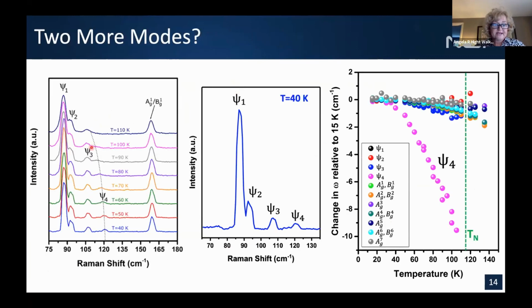So as we cool down even further, remember that transition temperature, the Néel temperature, was near 118. We begin to resolve two more features, such that if we blow up the 40K, we actually can now count 4 modes. So what we plot on this far right is the temperature dependence of all the regular phonons, as well as these 4 new features. You can definitely see the temperature dependence of Psi4 is quite different from any of the other phonons.